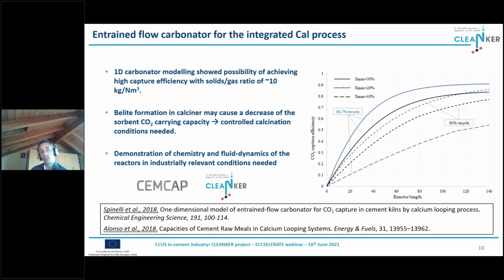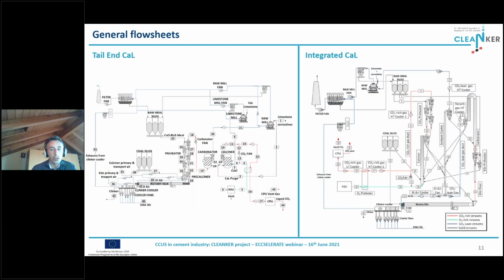So as you can see, in order to achieve a significant CO2 capture efficiency, we need a very long reactor, and this is mainly due to the high superficial velocity that we have in entrained flow systems, up to 15 meters per second, but also due to the kinetics of the carbonation reaction. So simulation results of the one-dimensional reactor models and the optimized steam cycle were imported in the overall zero-dimensional model, which reflects the scheme here presented for the tail end and the integrated case, to obtain the final performances.